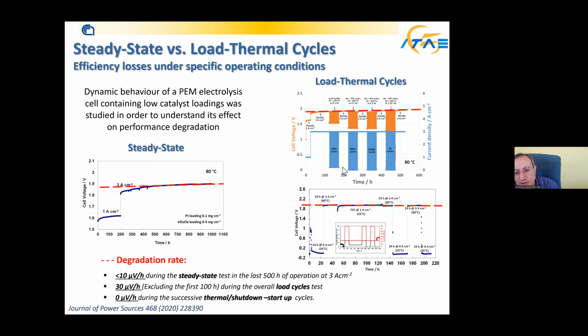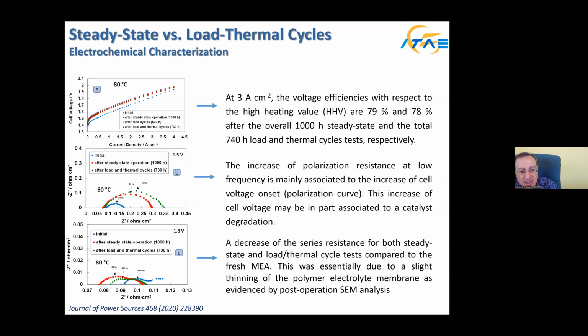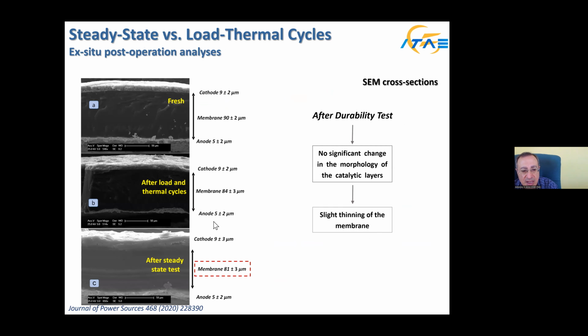We have also observed that during operation of the system, degradation under duty cycles was a little bit higher than under steady state. Degradation means a loss of efficiency with time, and this is essentially related to the electrode behavior, much less to the membrane.